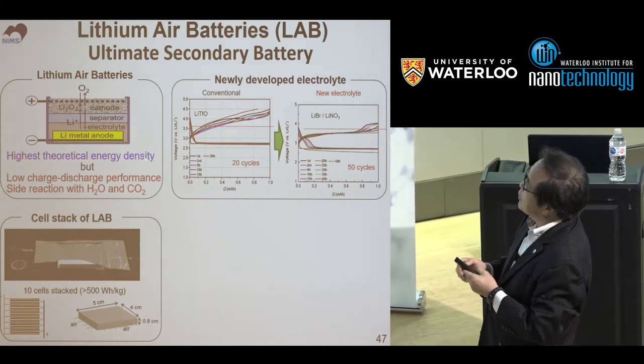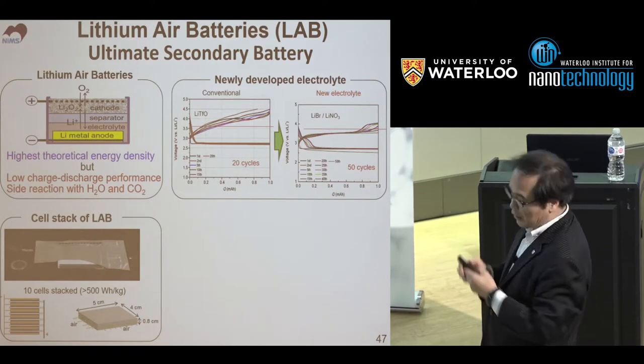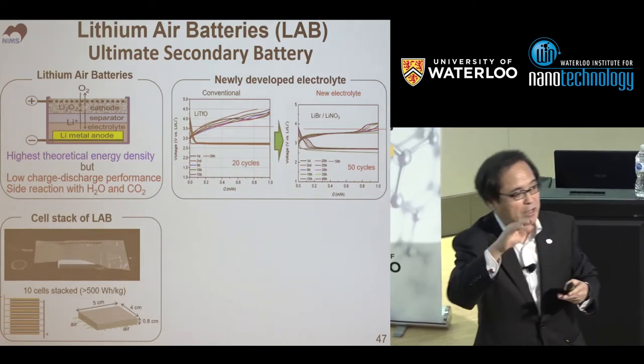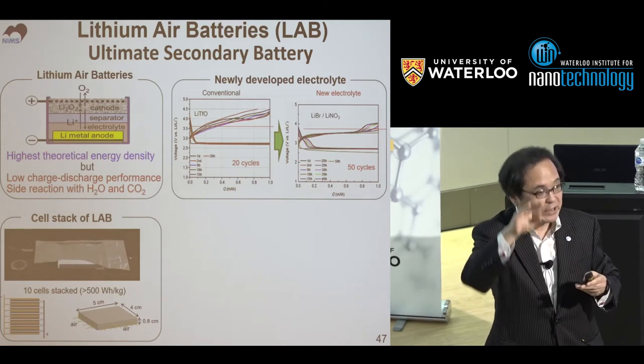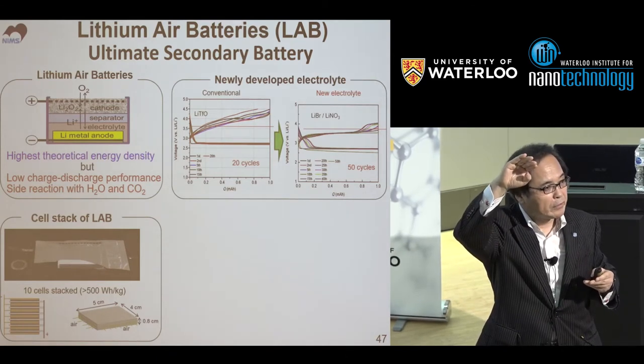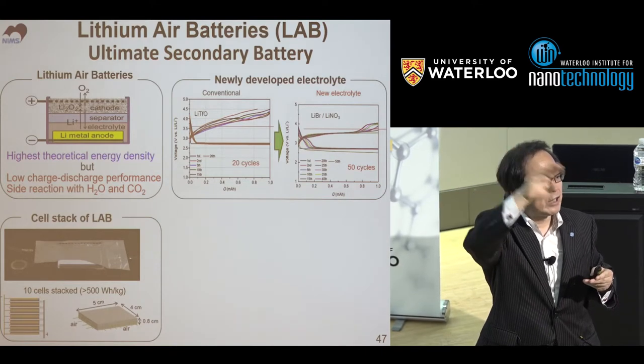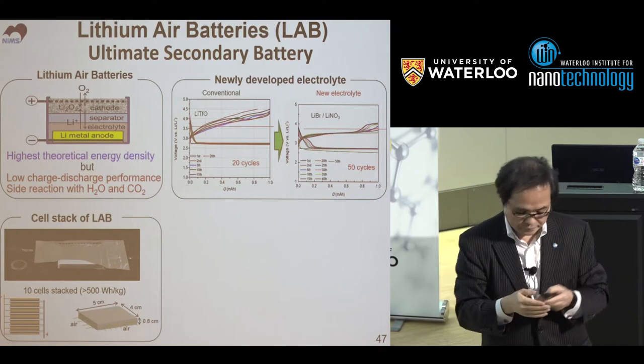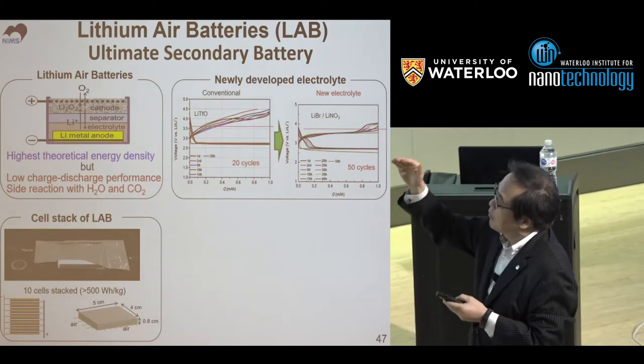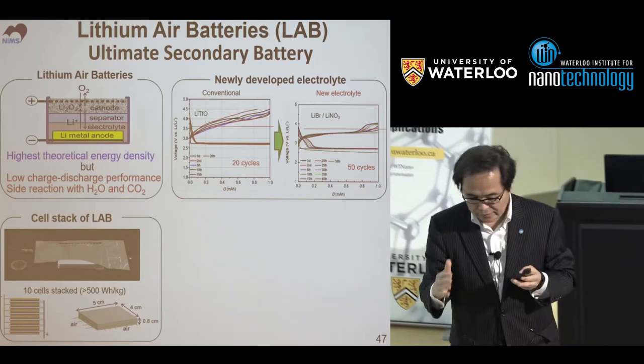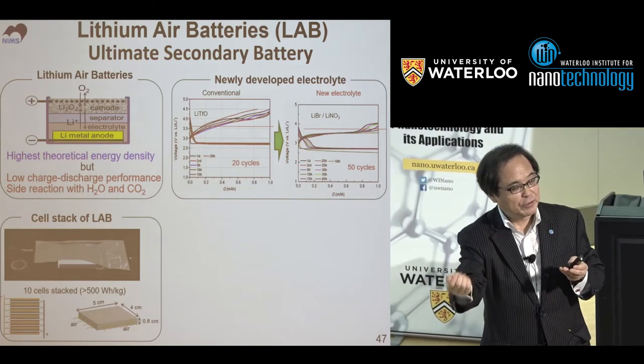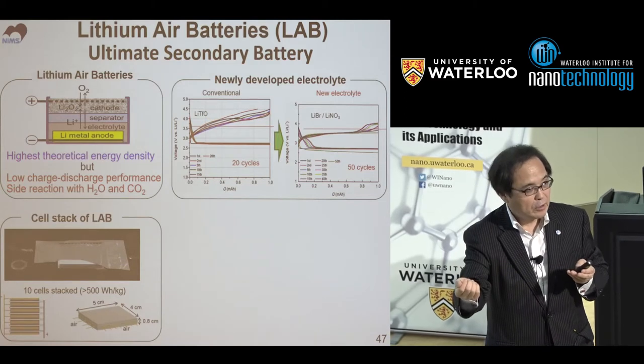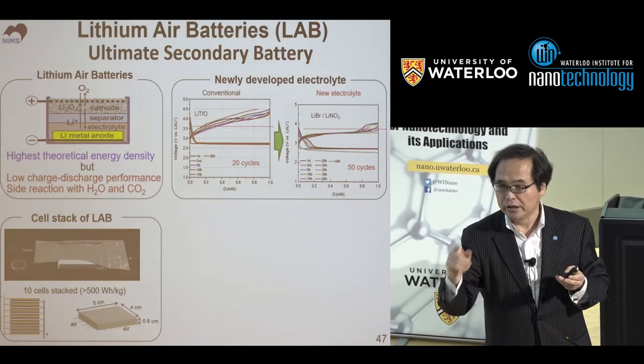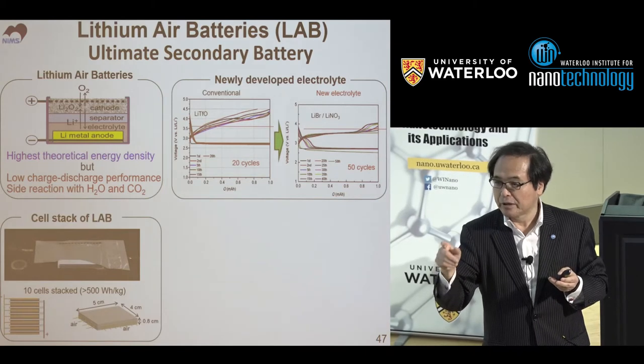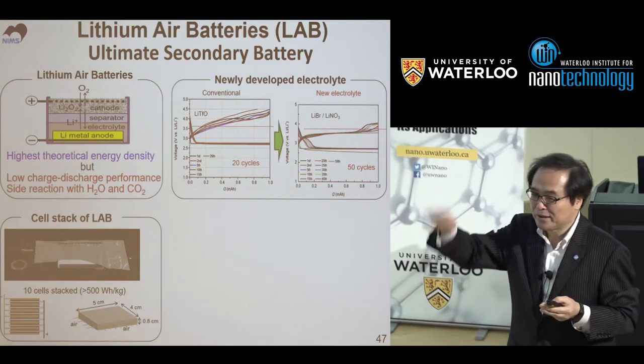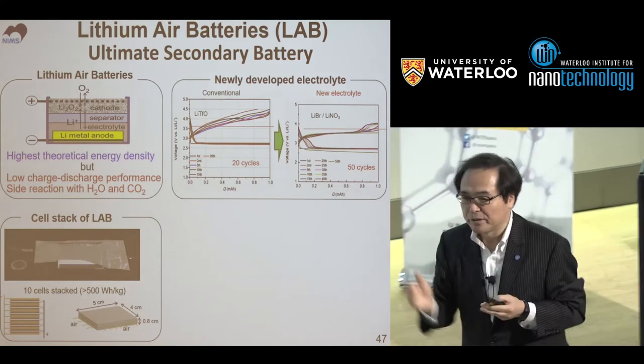For the first problem, we developed a new electrolyte by a combinatorial method, and the charging and discharging property has increased. Now we can repeat nearly 100 times, though not 100 yet. However, it is still much, much lower than expected. When we use this in a vehicle, the cycling number is expected to be more than 10,000 or several 10,000s. So a much, much better system is necessary.